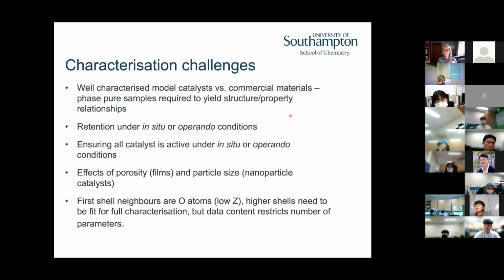The spectroscopy people will tell you you want more sample in the beam, to a limit. But the electrochemists are going to say, but if I make it too thick, then I just won't know what's going on. You have to worry about the porosity. Are you getting good diffusion through your film? And you have to worry about, as I said, the particle size. The smaller the particle, the more surface sensitive the measurements are going to be. And in terms of catalysis, it's pretty much going to happen at the surface.